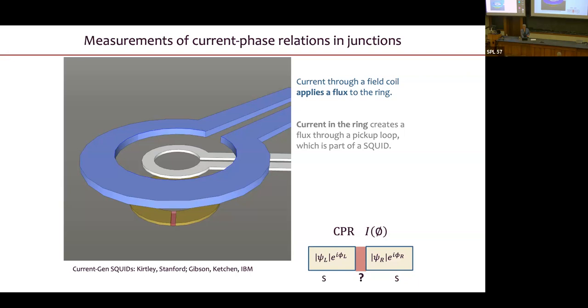And then that current that flows in the ring in turn creates a magnetic flux through a pickup loop, which is part of a SQUID. Okay, so we measure the current in the ring versus the applied flux. And then just by applying multiplicative factors of the very calculable mutual inductances, we then determine the current phase relation of the loop.